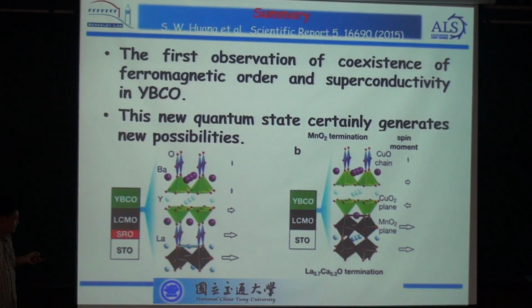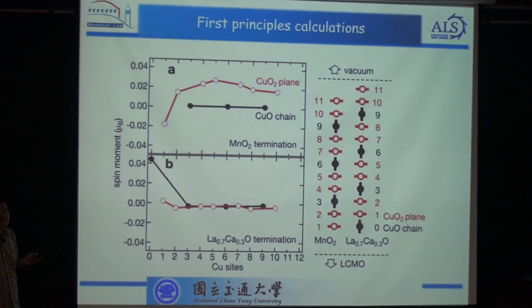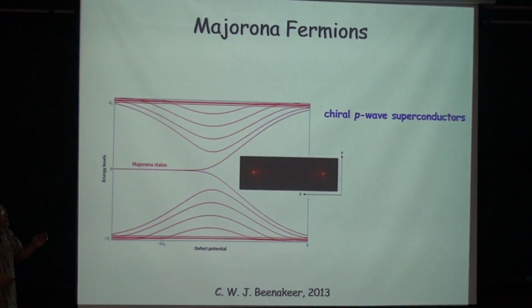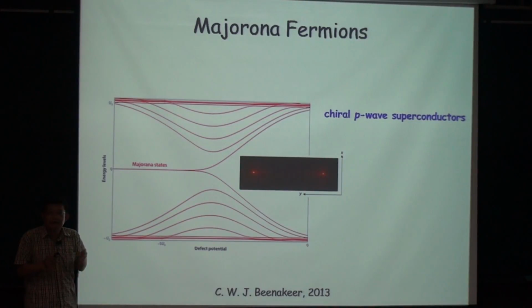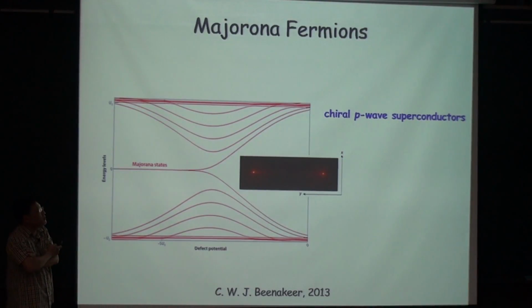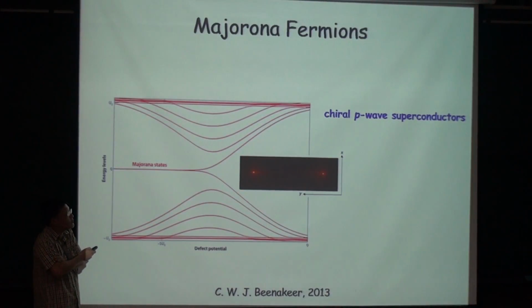But let me answer your question first. Mainly it should still be d-wave, because the induced magnetic moment is actually only 0.024 Bohr magneton per copper. But once you have some mixing of the d-wave and the ferromagnetic order, it is possible that you will induce some kind of p-wave superconductivity. For the past few years, there's been a new field: in nature, we do not have p-wave superconductivity. No material actually reveals evidence of p-wave superconductivity. But theory also tells us that if you have some coexistence of ferromagnetism and d-wave superconductivity or s-wave superconductivity,